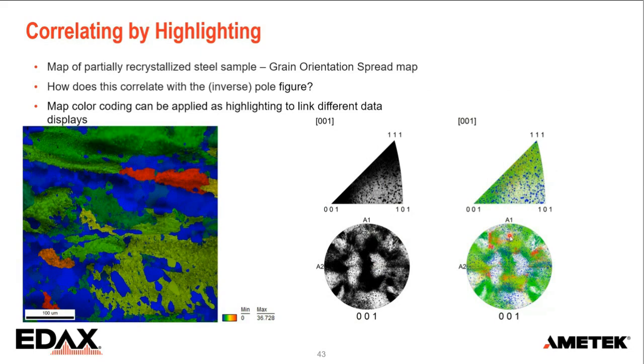They're just spread out over the entire pole figure. And in blue, the recrystallized grains. And I can also identify those over the entire surface of my pole figure. So this is a very nice way to correlate the pole figures, inverse pole figures, with a map, so you can separate certain fractions visually.